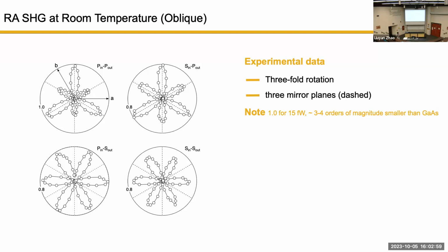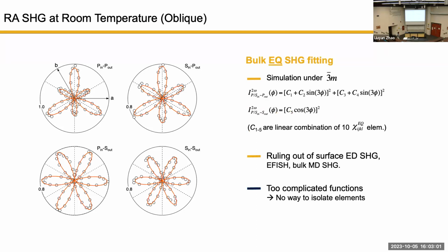And because the structure information is so well known, there's an inversion symmetry. So then we know that this signal will just come out from the so-called electroquadrupole process, because the electrodipole process is suppressed since the inversion is there. But yet we can still get this good data quality. And we can simulate the electroquadrupole response under this symmetry point group and use the functional form to fit our data. The fits are the orange lines. It fits pretty well.